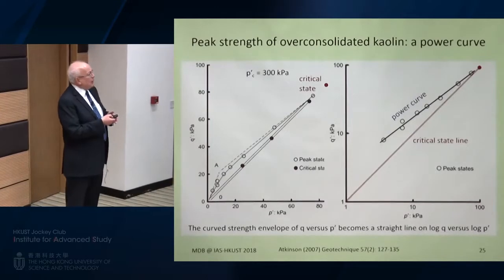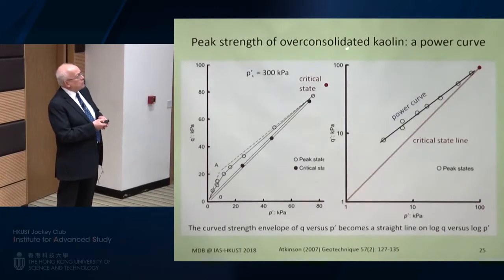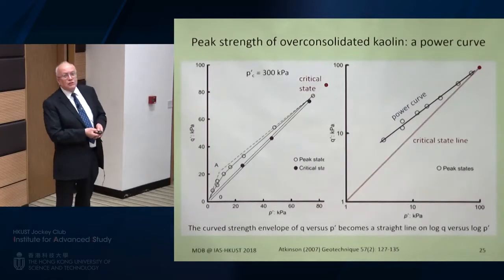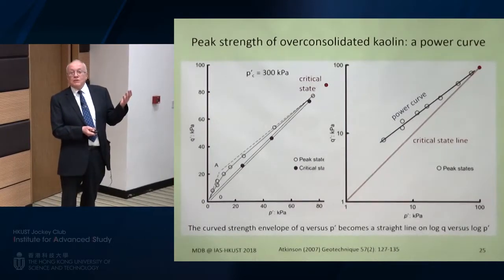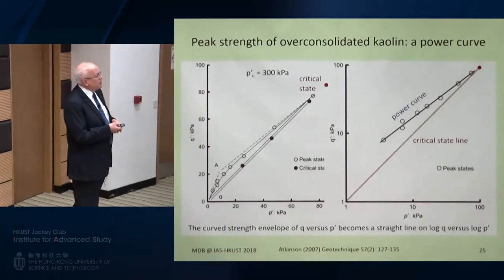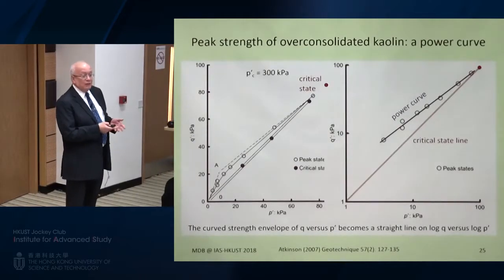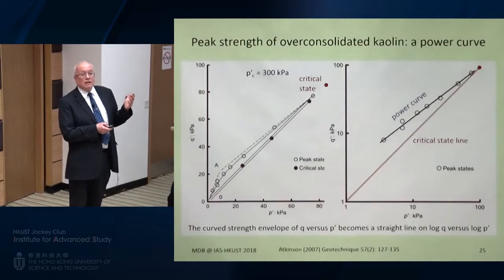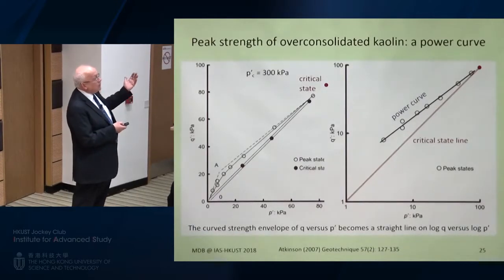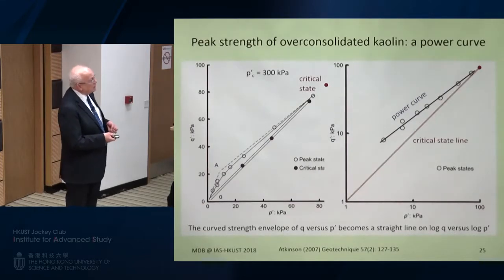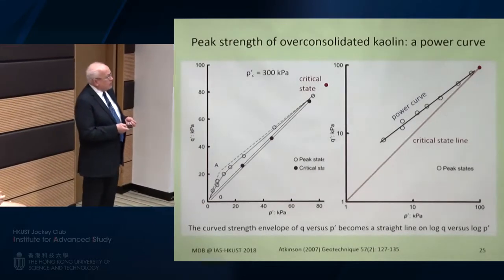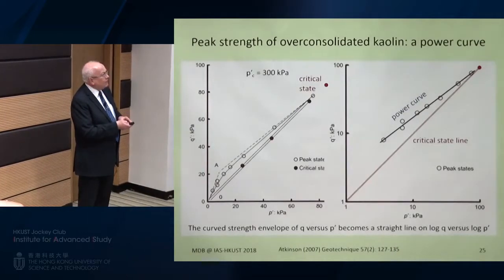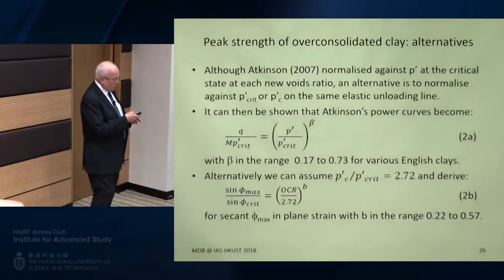Well, you don't have to mess about to that extent if you just plot log Q against log P dash, which is what I ended up doing with the sand. Log shear strength against log mean effective stress. It's a power curve. It's the same sort of power curve I've just shown you for sand. So that was sands before. This is clays. So this is the peak strength, and if you push it over the peak, it softens down onto the critical state line. I think that's all I had time for on clays. Well, I sort of summarized.